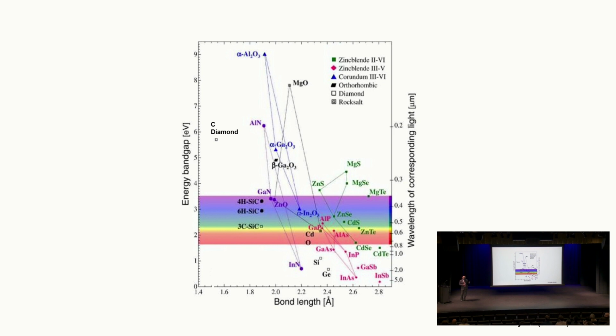If that is the case, we asked ourselves a lot of holy grail questions. If diamond has a band gap of 5.6 electron volts, without changing the composition, without chemistry, just by mechanical means, can you change the band gap of diamond from 5.6 to something much lower, say very close to compound semiconductors in this range? Can you do that? If so, what kind of strains does it take? Can you do that with the kinds of strains that we have already demonstrated for nanoscale diamond, which is up to 9%, 10% or so?